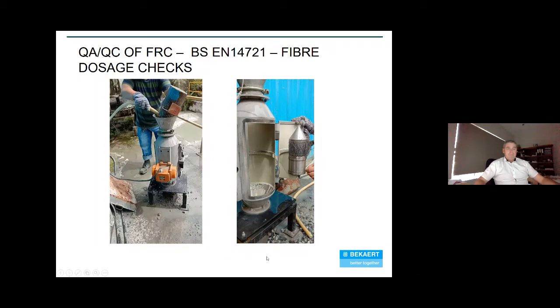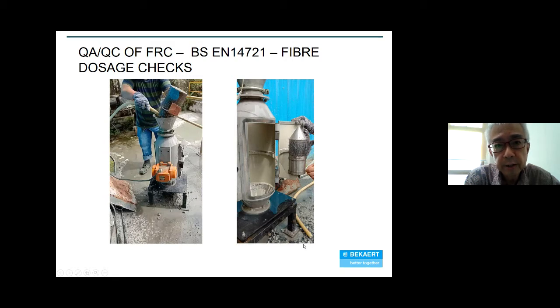Hello, everyone. Let's start with QA/QC of fibre reinforced concrete. There are two main QA/QC tests that we do. The first one is fibre dosage checking, as you can see with the equipment here, under the standard BS EN14721. You pour the wet concrete with fibres into this equipment, and the magnet in the center will catch all the steel fibres, and with that you can easily weigh them and find out the dosage of fibre you use. This test takes no more than 15 minutes. The traditional way of washing by hand will take at least 30 to 40 minutes.